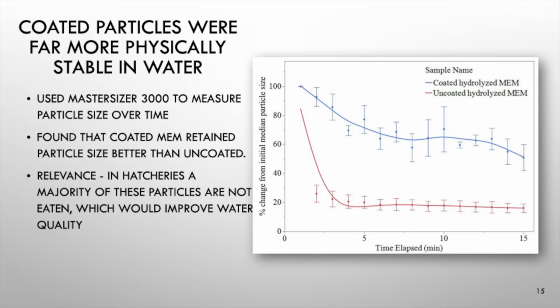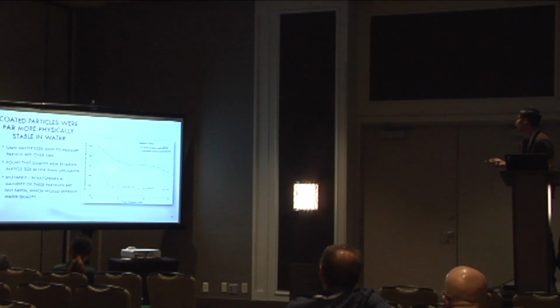And then on to particle stability. To measure the particle stability, we submerged coated and uncoated diets in salt water and then ran them through the Mastersizer 3000 machine, which took measurements of particle size every minute. As you can see from the figure on the right, the blue coated diet curve showing the particle size over time was able to retain much larger particle size over time compared to the uncoated, which rapidly degraded and fell apart.